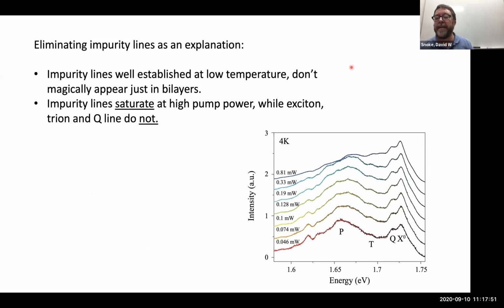Okay, so first of all, reasonableness says it's not some impurity, because impurities don't just magically appear in bilayers that aren't there in monolayers. And it's not an indirect exciton, because we know where those are. A third piece of evidence: a typical way to tell the difference between impurity lines and excitonic lines is that the impurities saturate because, again, there's only so many of them. So if you turn up the pump power, you will overwhelm them. But the trion and the Q line are excitonic in nature, and so they scale linearly with the exciton population. So at high power, you can see now that the quaternion, the exciton, and the trion are outweighing the impurity luminescence. So the quaternion line is not an impurity line, or I'll call it the Q line. You be the judge whether you think it's the quaternion line, but it's not an impurity line, and it's not an indirect exciton.